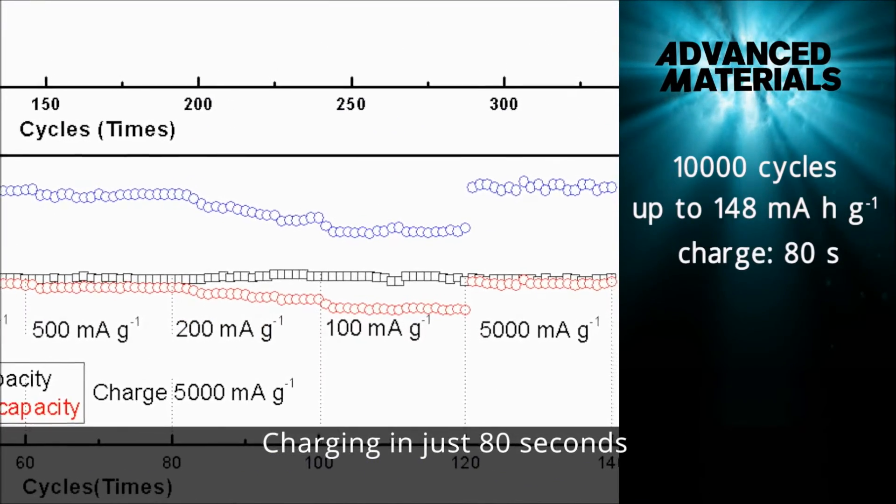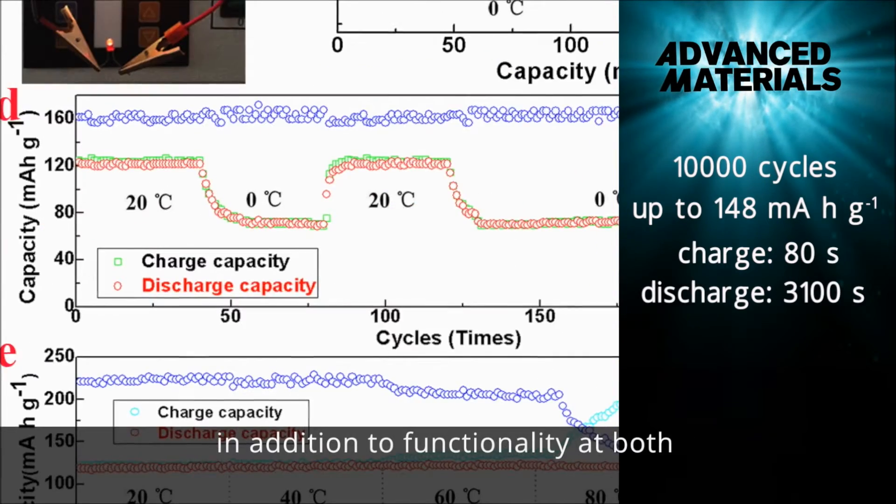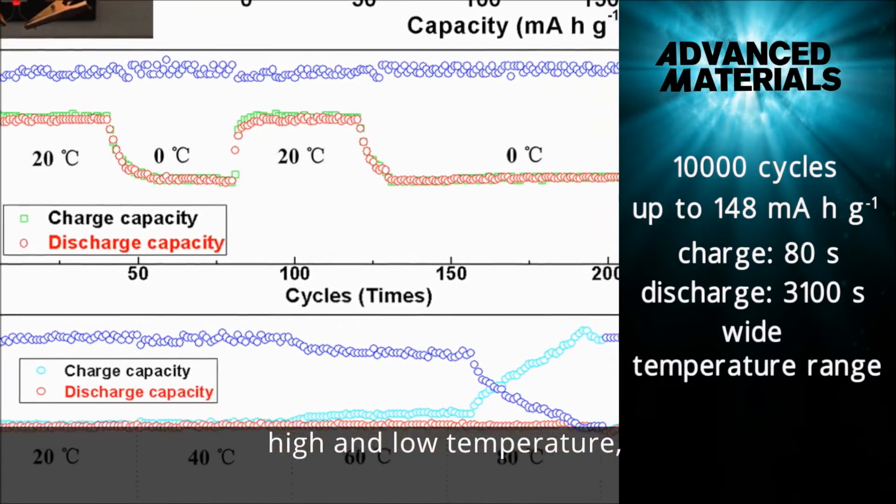Charging in just 80 seconds compared to discharge for more than 3,100 seconds, in addition to functionality at both high and low temperature, make the battery promising for applications in public transport and portable devices.